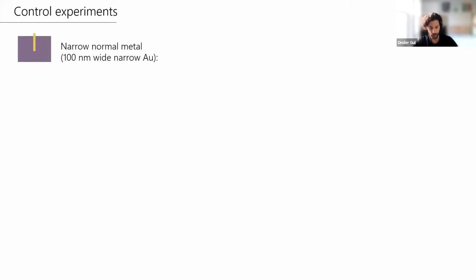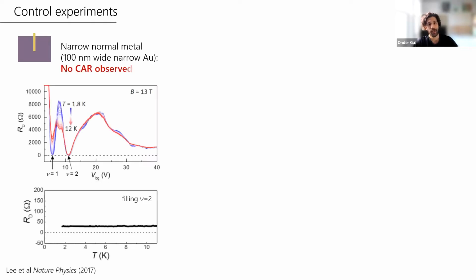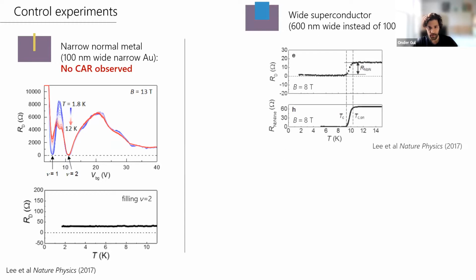So we have done control experiments to pinpoint the physical mechanism of the observed negative signal. In the first control experiment, we fabricated a device with a narrow gold electrode as the drain. This device shows a positive non-local signal for both integer fillings at high magnetic fields, and there is no temperature dependence. In the second experiment, the narrow superconducting electrode is replaced with a wide electrode. Also here, there is no negative signal.